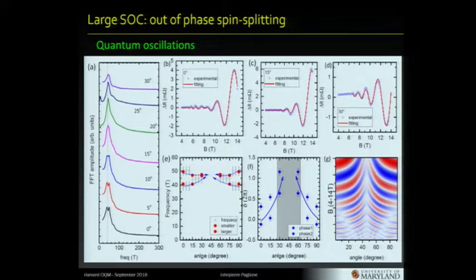The other thing that we can pull out of this that's quite interesting is the actual phase shift. So there's a relative phase between the two frequencies, but there's also an absolute phase, and that's called the Berry's phase. So the Berry's phase is doing something quite interesting. It's plotted in units of 2 pi here versus angle. It's going from 0 to 2 pi. So at some point, it actually goes through pi Berry's phase. It's quite strange. So that part we don't understand. There's some topology, there's some Berry's phase that changes as a function of angle. It's probably due to some spin orbit effect or texture on the surface.